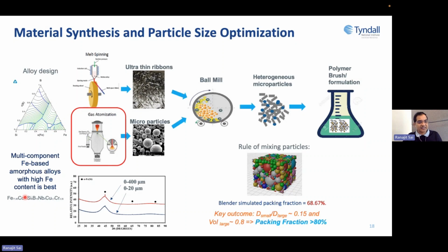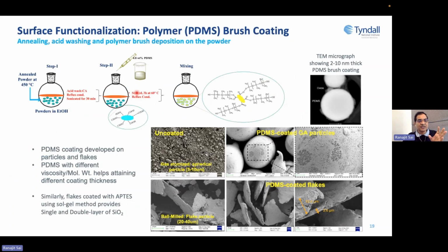We did some alloy design, some very fancy Fe-based material. Then we got them fabricated through our partners and collaborators. And then we did some ball milling to thin it down to appropriate size and appropriate thickness. And then we make heterogeneous particles. Sometimes we use spherical particles only, but with different size distribution through some simulations. And then we do some sort of surface treatment. And once we do the surface treatment, then we have nicely coated particles or flakes.